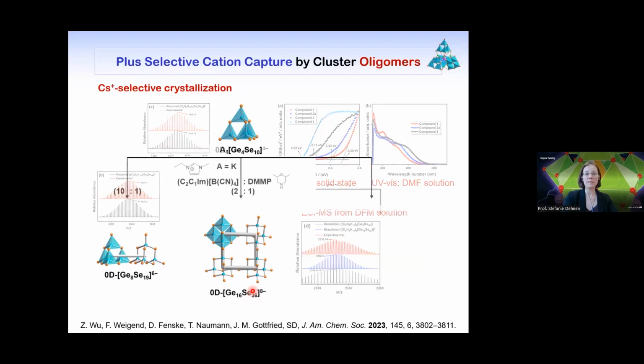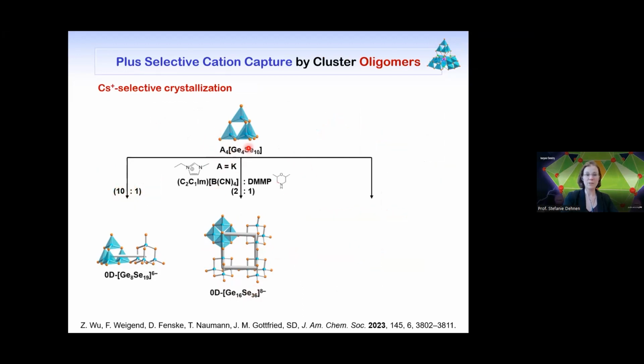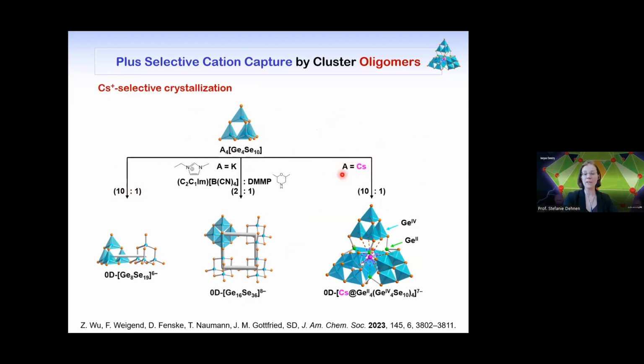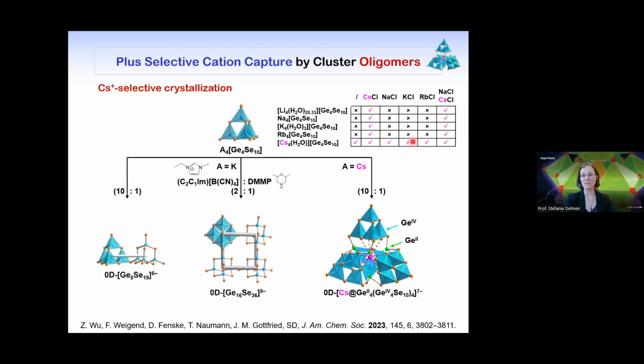If we then even change the cations that we use in our precursors and change it for cesium, we see an aggregation of 4 of these clusters. So another type of tetramer, but here we have a cesium included in the cluster molecule. This gives it first a larger size, and second, it is even better soluble because it's an internal counter ion. So the overall charge is just 7- instead of 8- with a larger number of atoms. So we can say that this is a very selective thing. None of the other alkali metals want to be in here for reasons of the fit of the sizes. And so this internal charge reduction gives it an even higher solubility.